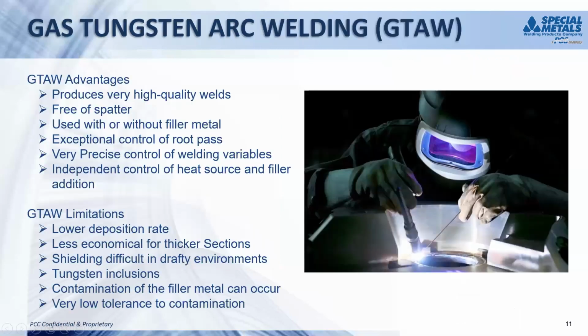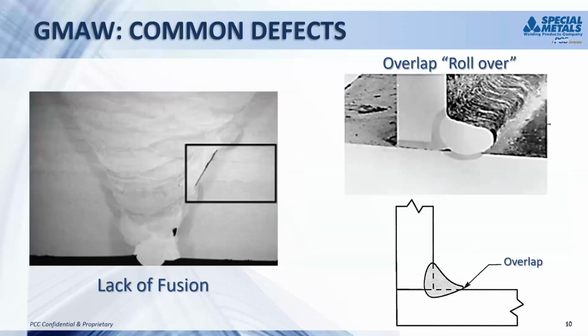Just for anyone doing robotic welding, sorry, John, the rollover can be a very big problem in tight corners with robots. With steel wires, it's pretty common to be able to almost do a 90-degree turn with those robots without breaking arc because of the fluidity of the steel. When you get into the nickel alloys, they're just not that fluid. You have to be a little more careful, and sometimes if you're in a very sharp corner, you may want to break the arc, pause for just a second just to avoid that buildup as that robot arm turns and doesn't really move the puddle. It just rotates to get around that corner. Next slide.